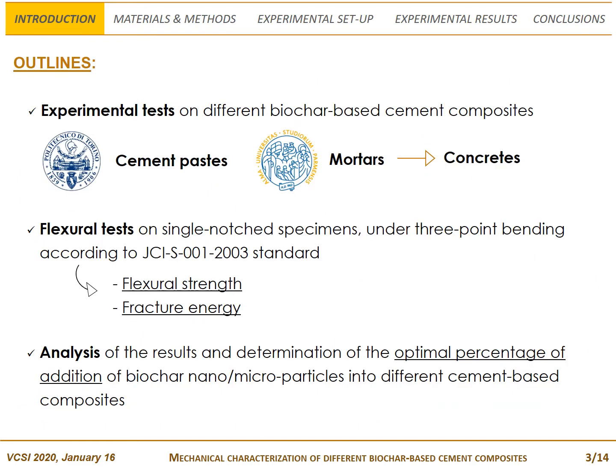The experimental program consisted of 2 series of tests. The first on cement pastes, carried out at Polytechnic of Torino, and the second one on cementitious mortars carried out at University of Parma, as a first step to develop environmentally friendly green concretes. Both cement pastes and mortars were prepared by using the same biochar, added in increasing percentage up to 2.5% by weight of cement. Prismatic single-notch specimens were subjected to 3-point bending tests, according to the Japanese Concrete Institute standard, so as to determine flexural strength and fracture energy.